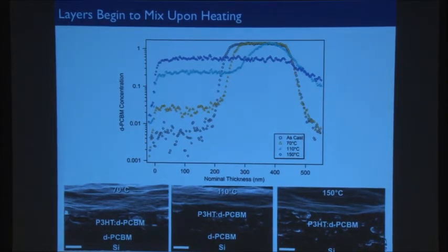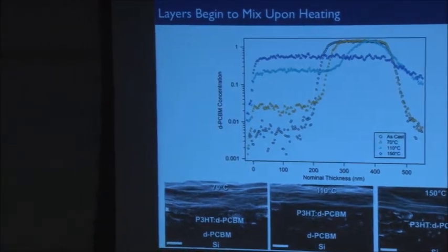This was a very simple experiment, and no one had actually done it at this point. And it's been repeated by a lot of other groups nearly at the same time. And there's some stories there about why that happened I can share afterwards. But what we found was that this thing is really miscible, right? These two materials really just do intermix at very low temperatures.